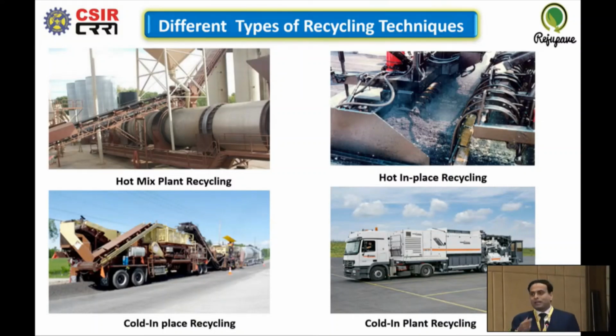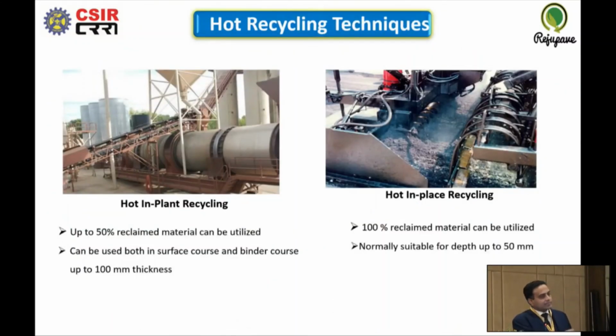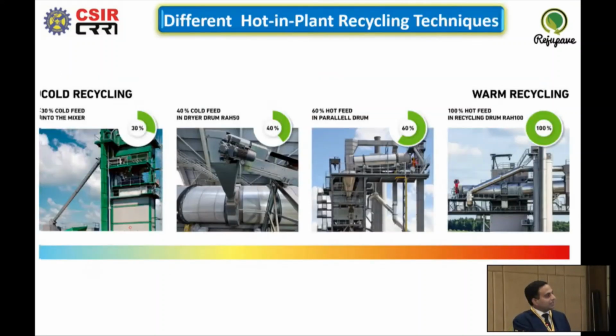Whatever the material is coming out, it is going inside the pavement. But in case of hot in plant recycling technology, since you extract the RAP from the bituminous layer and then segregate it into 2 categories, we have very good control on the mix properties. So with the help of that, you can really construct a good quality pavement surfacing at an economical cost. Up to this hot in plant recycling process, the maximum RAP utilization is 25 to 30%, but with the advent of this RejuPave technology, we have successfully utilized up to 70%.